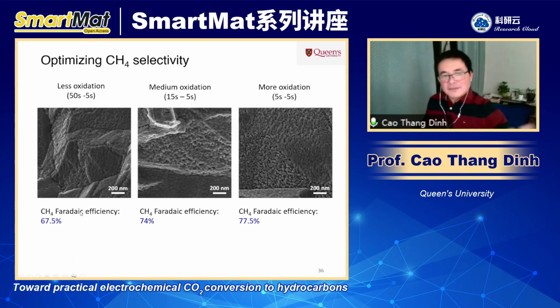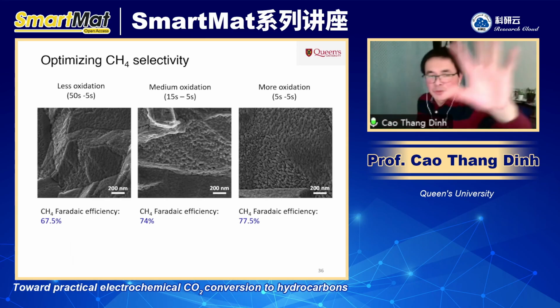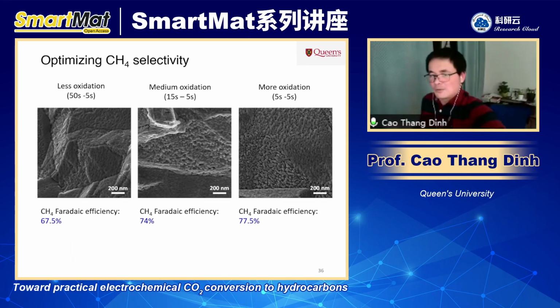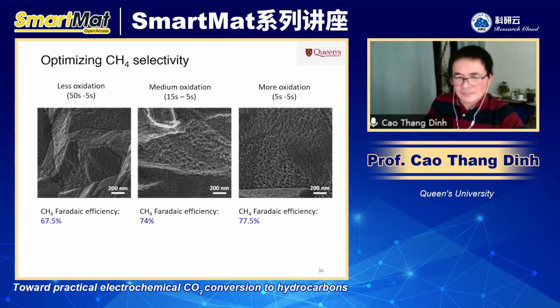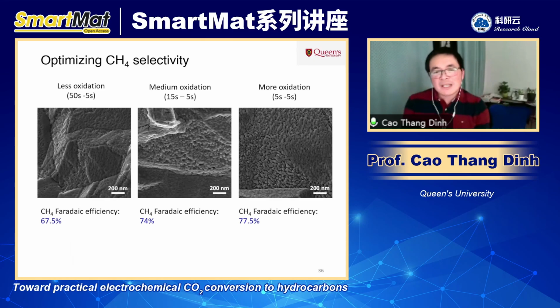And also with the different surfaces, you have different selectivity for methane, right? With the less oxidation, you have 65, 67%. All of them are at a current density of 250 milliamp, right? And as you increase the oxidation, you increase methane selectivity to 70, close to 80% here. So there's a strong link between the oxidation condition, the surface morphology, and the methane selectivity.